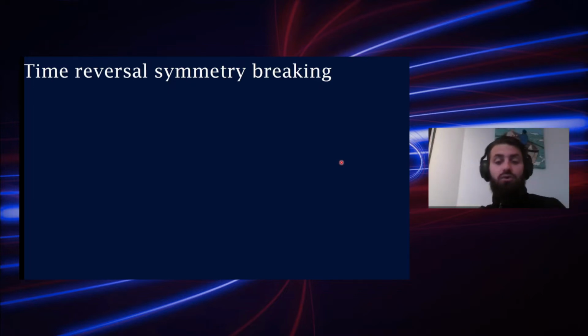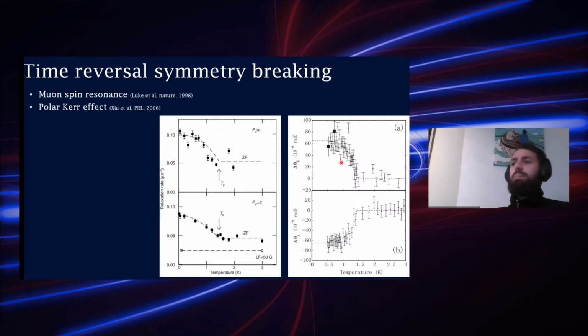Then the time reversal symmetry breaking, which is equaling the chiral nature of strontium ruthenate. The evidence for this was mainly the muon spin resonance experiments and polar Kerr effect that found local emergent magnetic fields below TC.